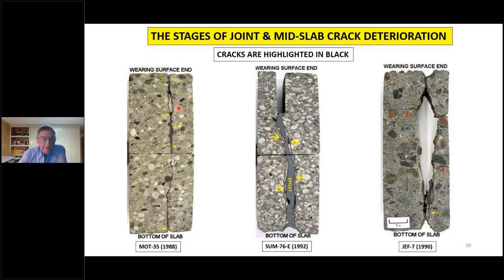But you'll see here in this one on the left where the arrows are pointing, I have marked under the microscope, taken a black pen and marked where the cracks are. A little bit of spalling here and a little bit of cracking at the bottom here. In the intermediate stage, there's quite a bit more material loss from the middle. This has been epoxied together to facilitate lapping or polishing the core section. Again, the arrows are pointing to cracks that are present in there, which are microscopic. They're very, very tight cracks.